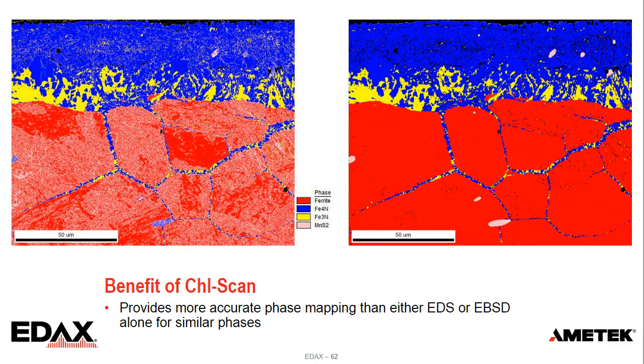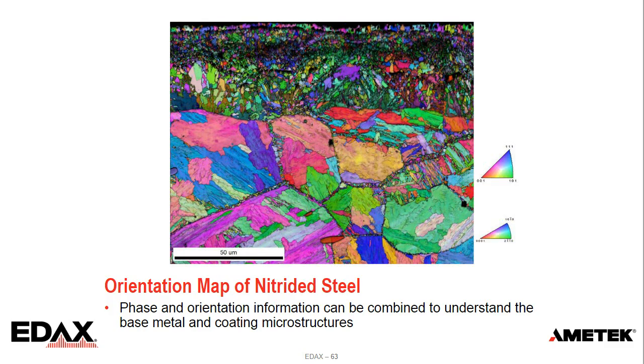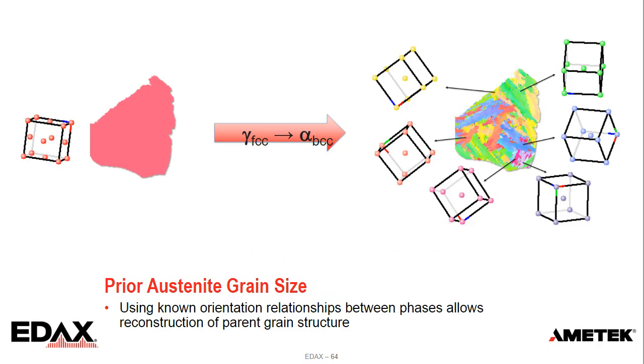And then we can look at the orientation information. And so this just shows the orientations for the different phases. There's different color keys that are used. And for the ferritic grains, these larger ones at the bottoms, these are called packets. And this just comes from the transformation from austenite to ferrite, where these patterns in here form a preferred orientation relationship in these packets. And so this is another application question that has been around for EBSD for a long time of measuring the prior austenite grain size.